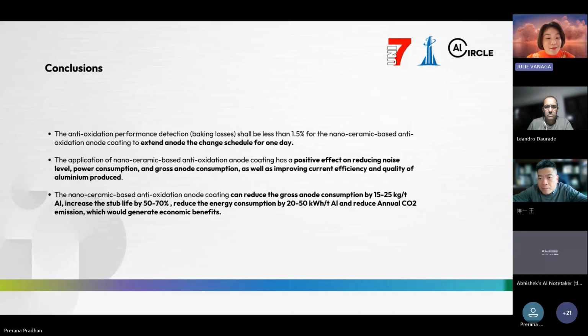Okay, well, let's come to the conclusion. So we are very confident with our product. After analyzing all these test results, all those practical data and on-site performance, we have drawn very clear and actionable conclusions about our nano ceramic based anti-oxidation nano anode coating technology, from 12 months of real production tests at 20 smelters. First is the anode changing schedule extension. When the anti-oxidation performance of the coating is less than 1.5%, the technology can extend the anode change cycle by 1 full day, a huge improvement for smelter production scheduling and efficiency. This is the first one we want to emphasize.